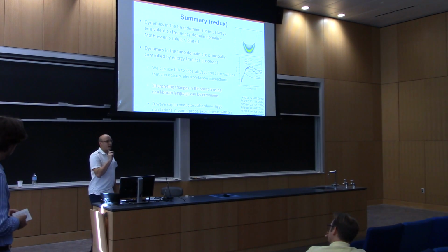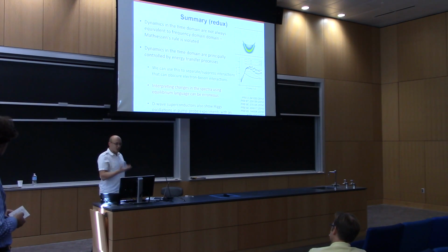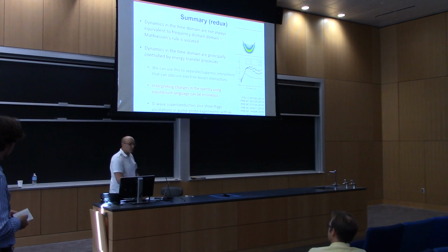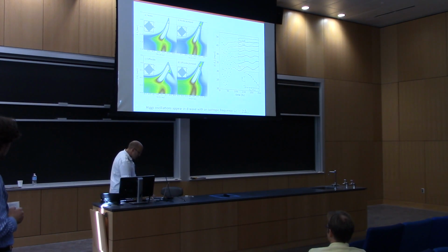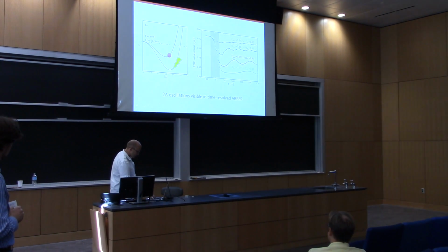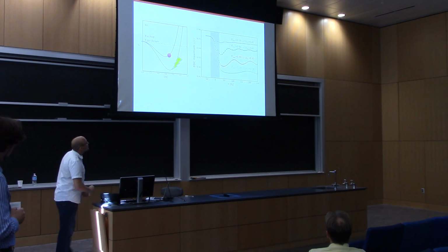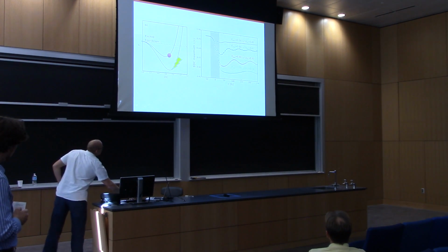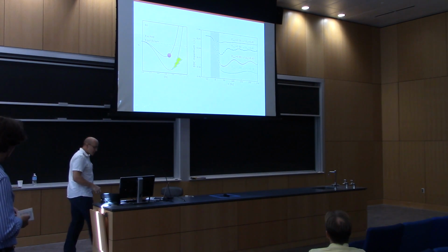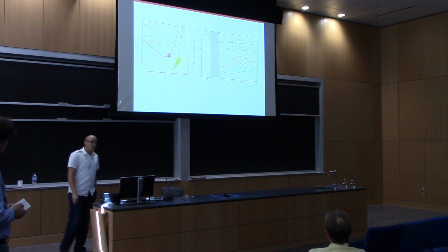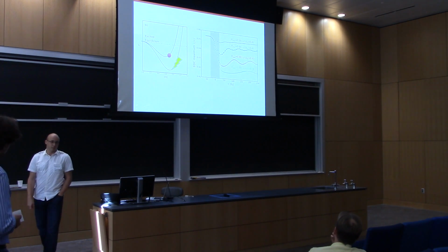One, that was sort of a cartoon picture. Right, we don't actually have increased temperature. We have non-equilibrium redistribution. On the other hand, yes, you are correct. We should see a change in the frequency. It should speed up as a function of time. And it's hard to see here, but if you do the analysis, you can actually see that the oscillations here, this one's a better one, I think, are somewhat slower than they are over there. We have some other data that shows this a little bit better. So yes, the oscillations do in fact speed up.